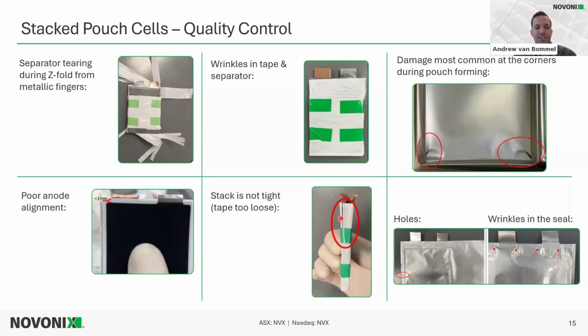In this case, the stack is not tight, the tape is too loose, so the tape will have to be adjusted when the tape is applied. And here's what I was mentioning. If the pouch formed is too deep, there could be damage on the corners. That could be an area where there's electrolyte leaking from. Here's some cases where there's holes, and another case where there's wrinkles in the seal. So these cells would have to be rejected, and more care would have to take place to get good quality pouch cells without these defects.